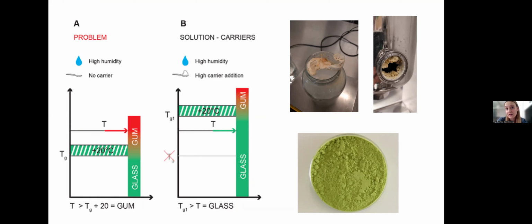The solution to it, especially in the industry, is to add carriers. Carriers are the high molecular weight sugars, mostly polysaccharides and proteins. When they are added to the raw material, they increase the overall glass transition temperature. So we move this problematic point, the glass transition temperature, and we ensure that we are not reaching this zone where the stickiness might occur. However, normally in the industry, to achieve this effect, especially working with ambient or high drying air humidities, the carrier content is quite significant, around 50% of solids of the material.